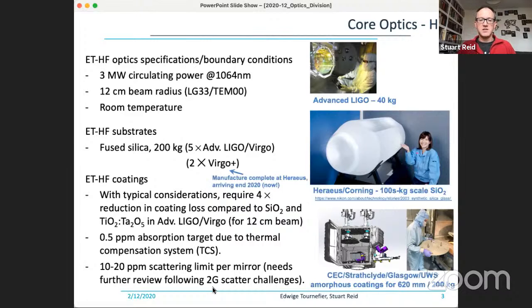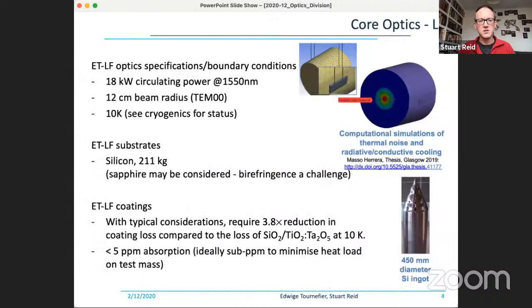The availability of coatings over large substrates of around 62 centimeter diameter is not really available at the moment, but there are plans in a number of labs. This is the system that's currently being procured in the UK from Cutting Edge Coatings in Germany, able to coat 2 620 millimeter diameter optics at the same time, and similar work in LMA to create the facilities for coating these large area optics.